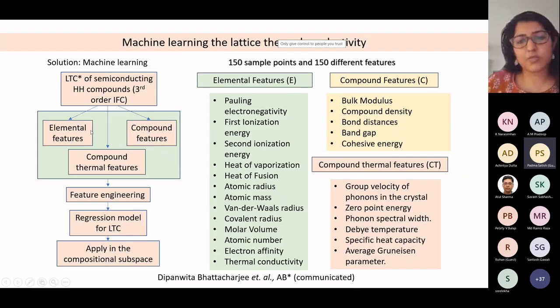So we took about 150 sample points where the phonon calculations have been performed accurately, and third order phonon calculations have been performed to calculate the lattice thermal conductivity from first principles.